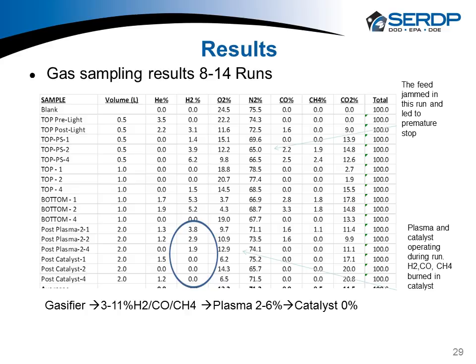Basically, we were making hydrogen throughout. To summarize, coming out of the gasifier, we had 3 to 11% of hydrogen plus carbon monoxide plus methane. When we went to the plasma, it was down to 2 to 6%. And coming out of the catalyst was 0, and that's just operator error on our part that we didn't have the parameters optimized. We had that extra air going into the thing from the plasma, and it was just basically combusting all of the energy stream in the catalyst bed.